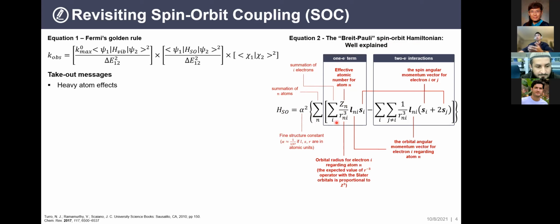So ultimately, you are looking for a somewhat fourth-power kind of relationship between your spin-orbit coupling energy and the atomic size. So that's why the heavy atom effect is really important, because spin-orbit coupling efficiency is very sensitive to the heaviness of the nucleus. There is also, you see the L and the S, which stand for the orbital and the spin angular momentum. So I will explain what these mean.